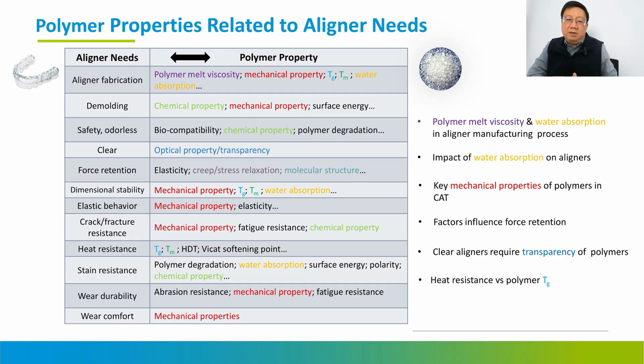So I would say if you use a softer material on the surface, then you have a problem: when it's soft, it means it's penetrable, which means soft material can always absorb a lot of colorful substances, such as red wine, coffee, and tea. So if you want better stain resistance, I always suggest you should use a smoother and more crystallized material, such as copolyester or hard TPU, and also have a lower surface energy on the surface, which means the stain will not stick to the liner. You can do the stain resistance test by yourself. Put the liner in coffee and see how fast it becomes stained.